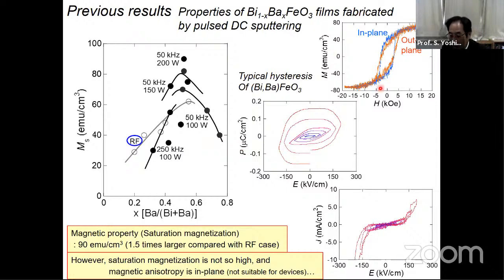These are typical hysteresis loops of this material. However, saturation magnetization is not so high, and the magnetic anisotropy of this material is in plane, not perpendicular. This property is not suitable for device application. Okay,